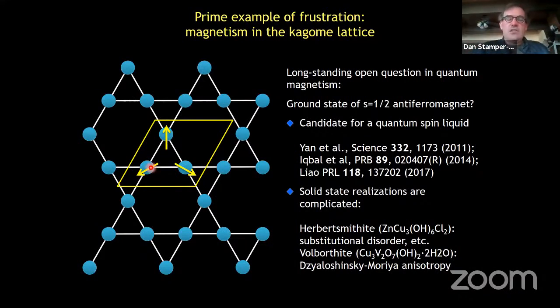Oh, really? Mm-hmm. And so if we, for example, just took this site, this bond, and we tuned its tunneling energy from being positive to 0 to negative, we would smoothly change the ground band of our lattice to a flat band. That would be really sweet. Unfortunately, nothing works as expected. And if you have atoms that are also interacting, then lo and behold, when you jiggle around the energy of these lattice sites, you just put a blowtorch and all of your atoms heat up, and it just turns into a big mess almost right away.